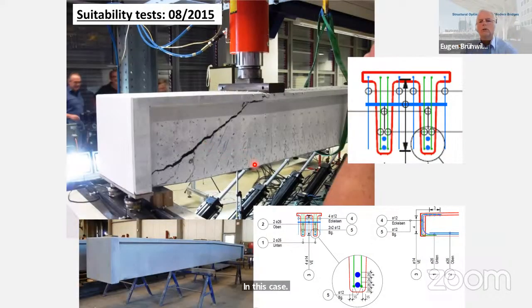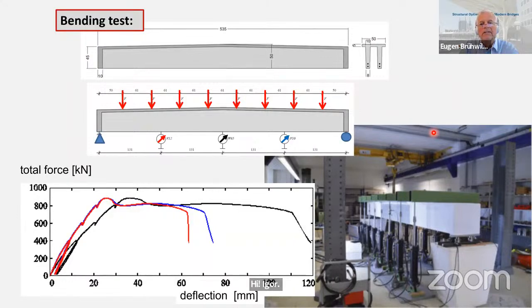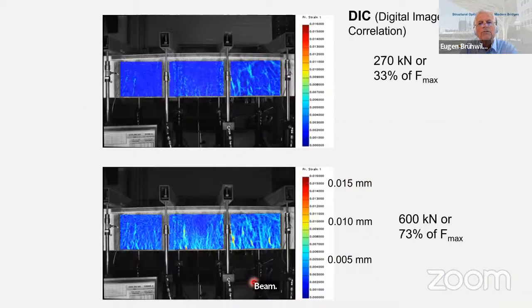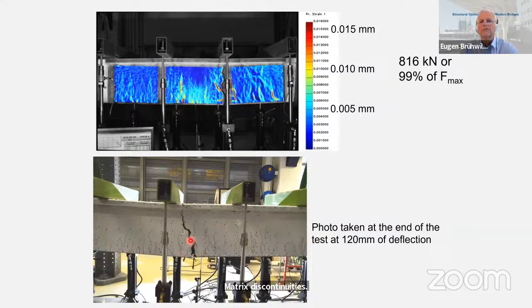We had the chance to do suitability tests on a high girder with 2 ribs. Here we have the bending case. So this simulates an equally distributed load on the beam. These are the recorded force deflection curves, with some digital image analysis in order to be able to recognize and identify some hairline cracks that you would not see by your eyes. So we have to go up to 73% of the ultimate resistance in order to see some hairline, I call them matrix discontinuities. And then, of course, eventually we have the fracture.